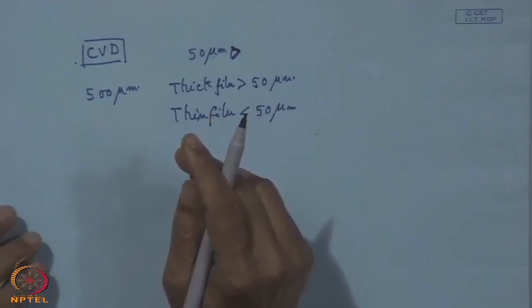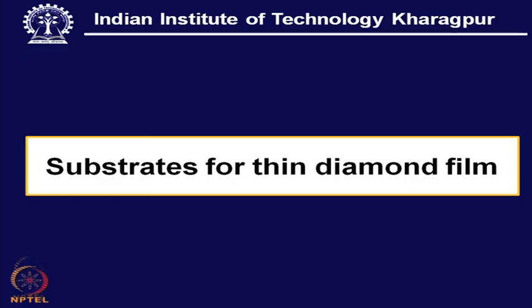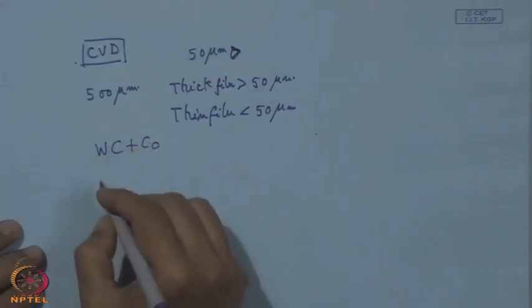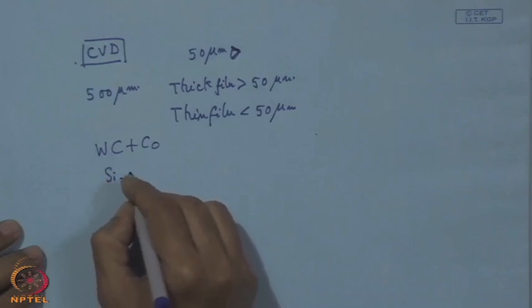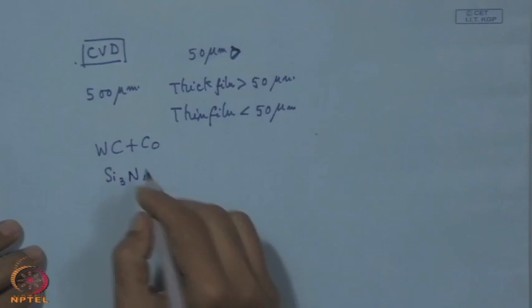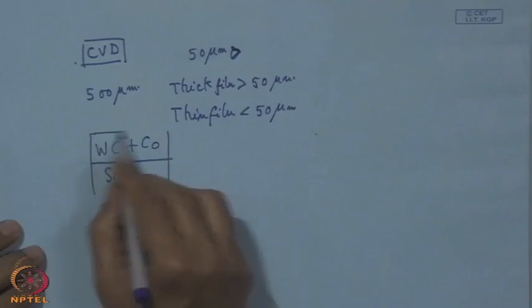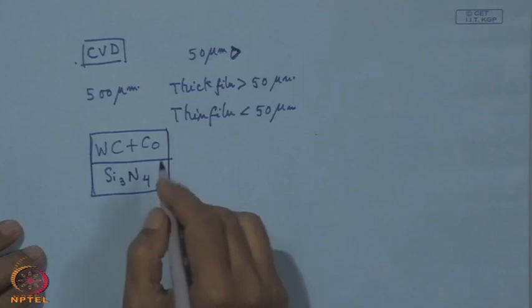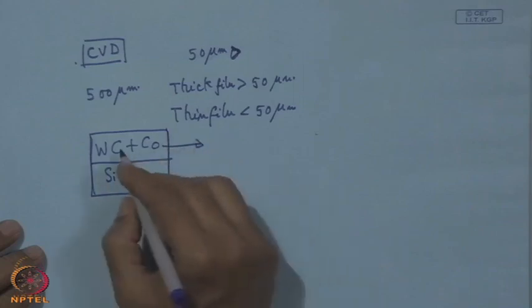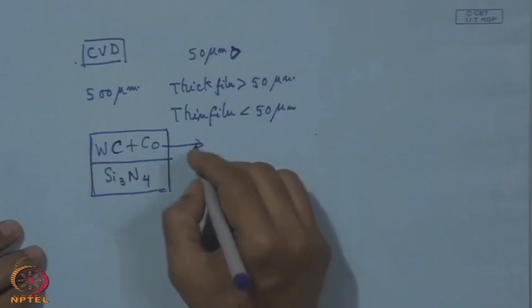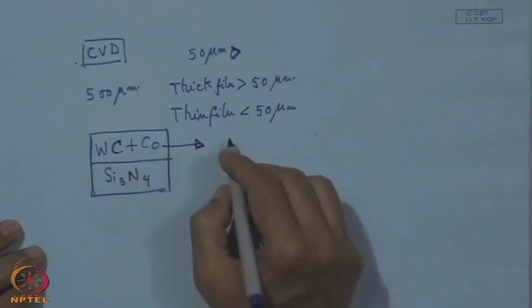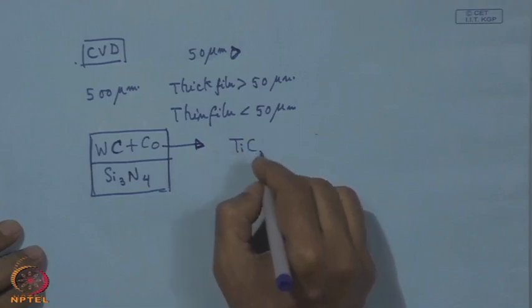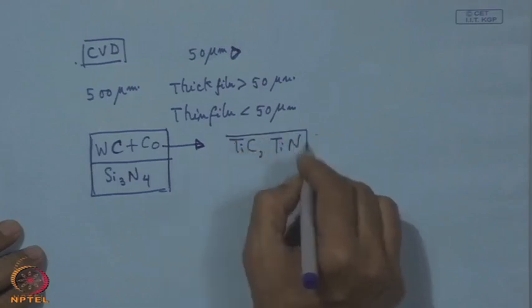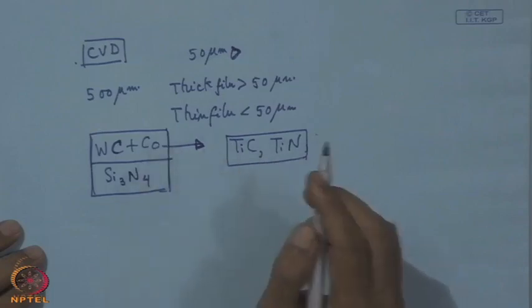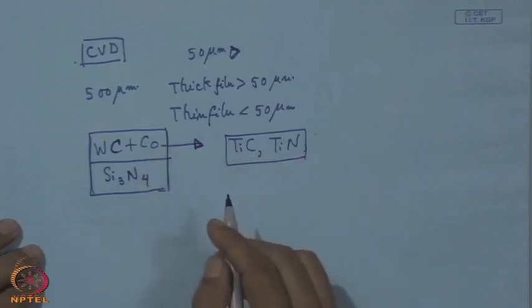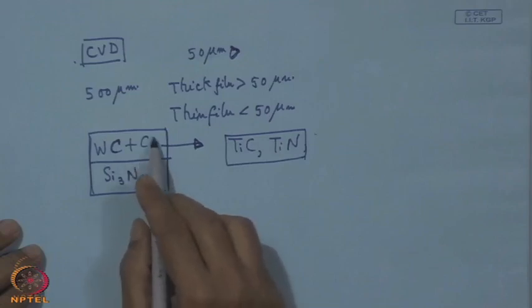Now, for this substrate for thin film, here we can have immediately tungsten carbide plus cobalt, it can be silicon nitride, Si3N4. These are the two substrates, but considering the toughness and other requirements, tungsten carbide plus cobalt is used as a substrate for all other types of hard coating like TiC, TiN, and the tool manufacturer will find it a substrate of immediate interest. However, the problem is here with the cobalt.